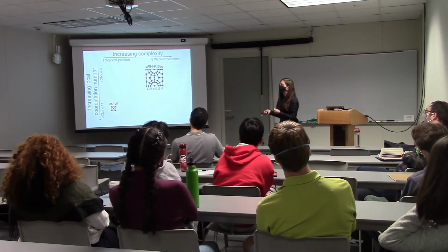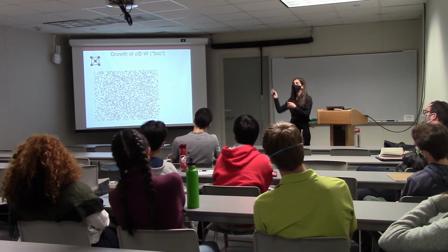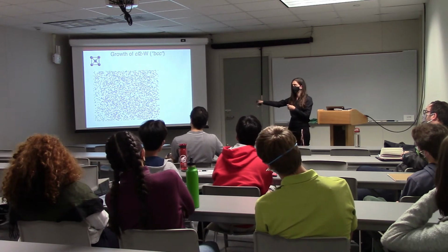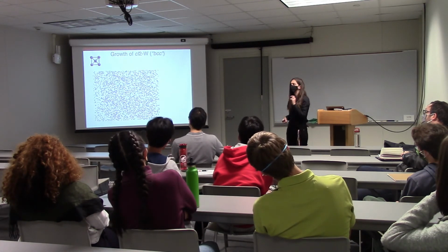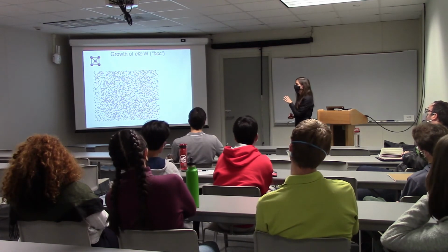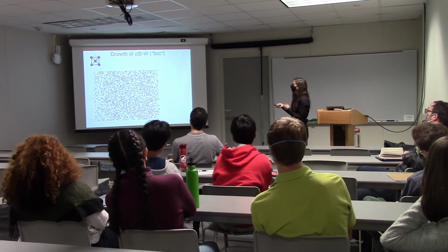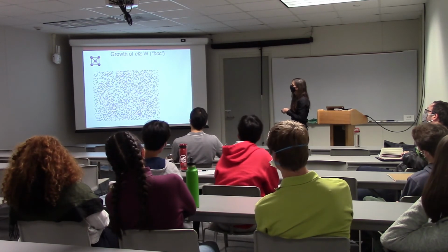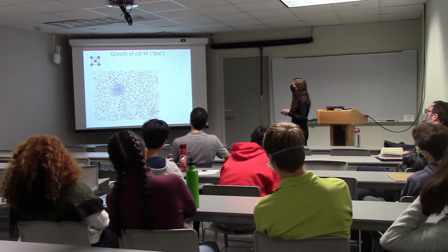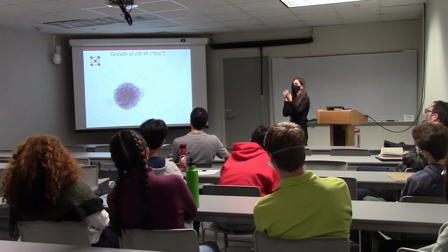So the one at the bottom left is simple. We look at how it assembles in the beginning. We're now applying this order parameter to the simulation. In the beginning, everything is purple. The number of clusters that we're fitting this to is actually not that easy to figure out, but here, trivially, it's 3 of them. We see a gas form. As the temperature is being lowered, you see that something nucleates. It starts being blue, and then at the core, red particles appear.